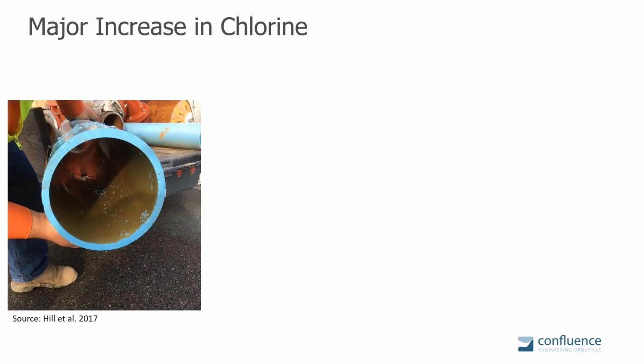An example of where we saw a problem with manganese, here's a system. This was fairly new pipe, only about 5 years old, but it had been receiving groundwater with non-detect levels of iron and manganese, but clearly enough in this case to be microbially adhered and absorbed to the pipe in this very slippery slime surface. And then when a surface water was introduced and high chlorine, the chlorine went from less than 0.2, 1 typical in this area, to up to 0.8 all of a sudden,